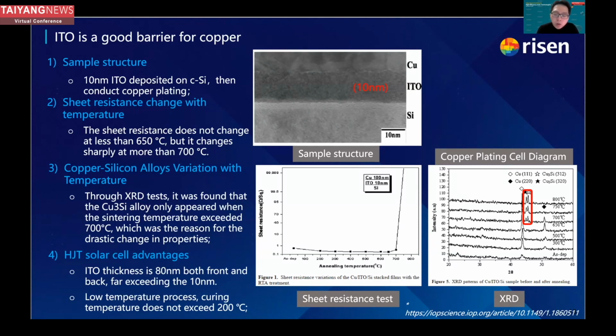As we know, for the heterojunction, we are using ITO as the TCO layer, and the silver paste is printed on this surface. So we tested this structure. As we can see, this is a sample structure we have created with silicon on the bottom and 10 nanometer ITO on the surface. And on the surface, we're using copper plating instead of low silver paste, because this is pure copper, which is a more stringent test compared to the low silver paste.